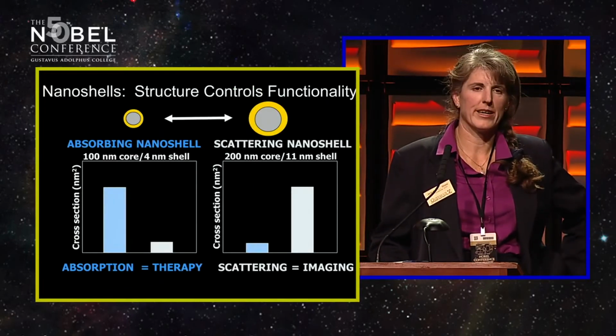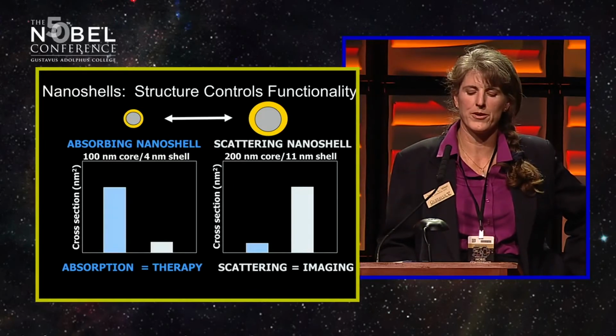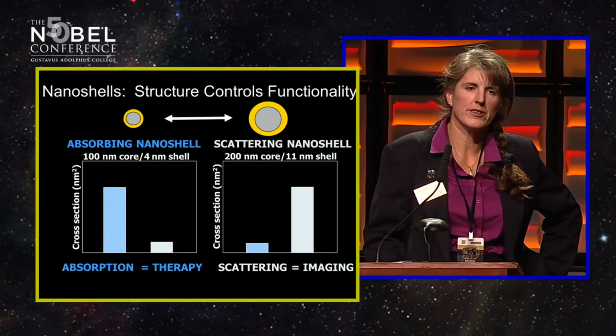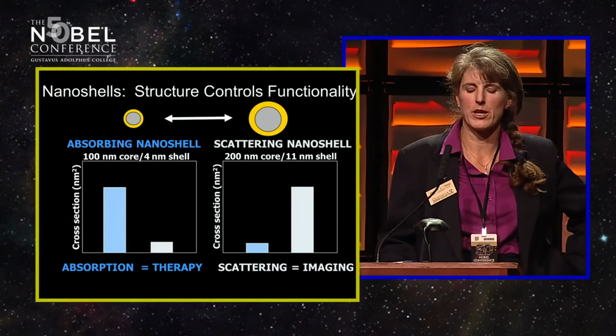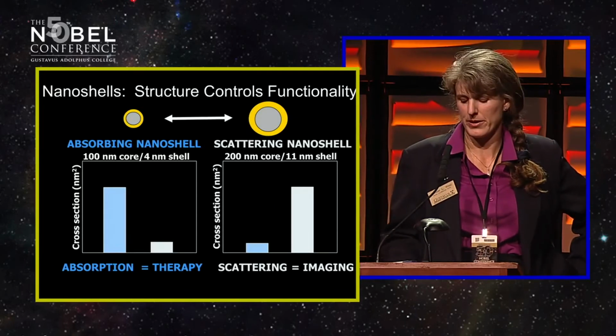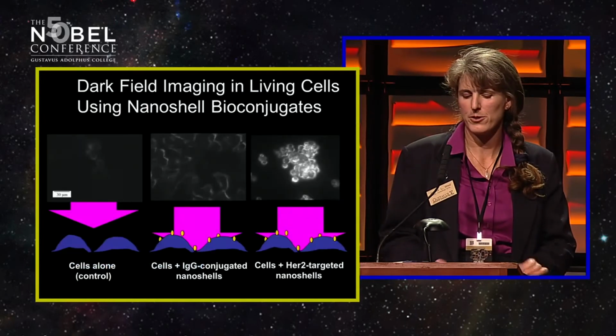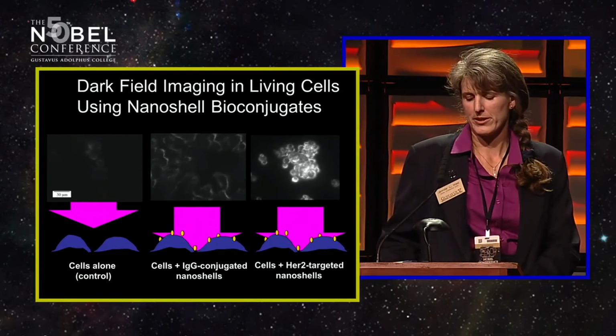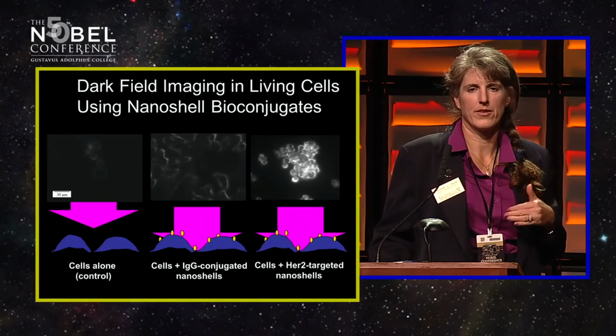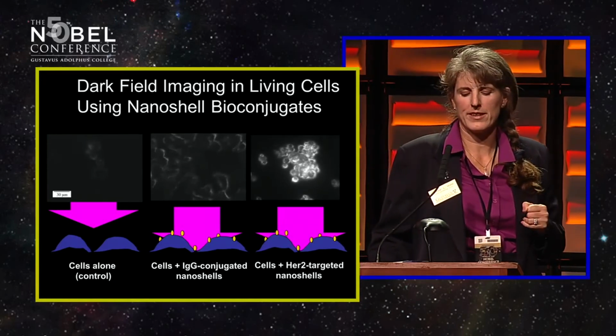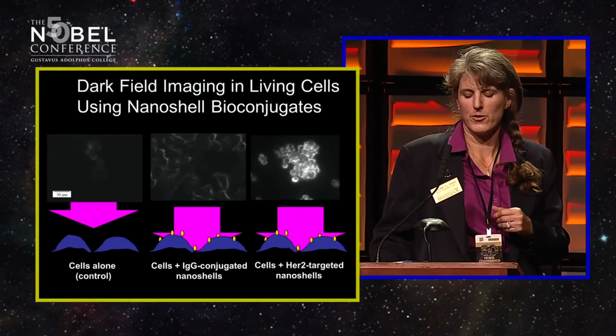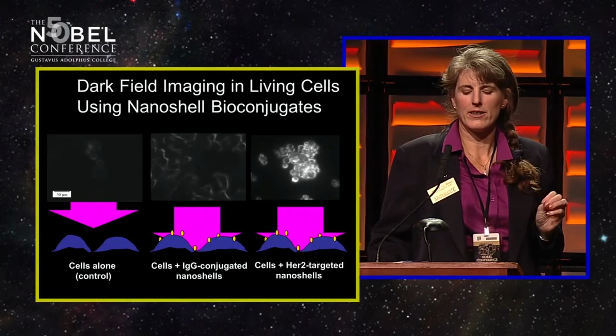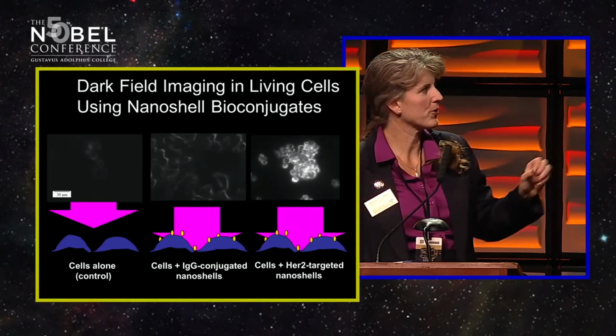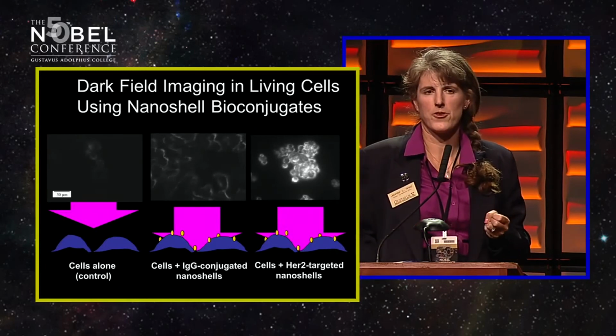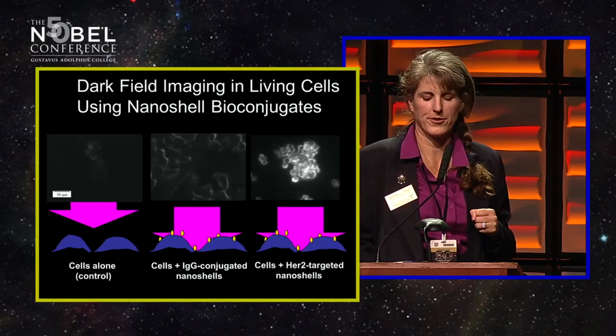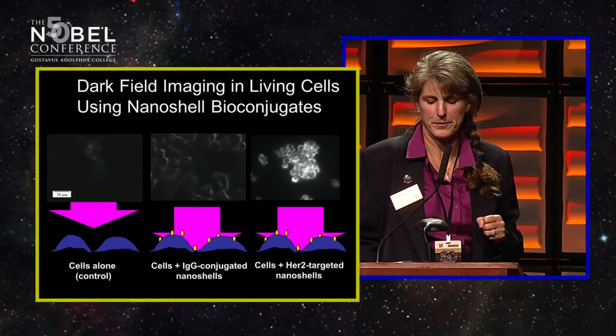So I've mentioned before, we can have our particles designed for absorption or for scattering for imaging. We've also looked at designing particles to be somewhere between these 2 extremes and to allow us to integrate imaging and therapy onto the same nanoparticle platform. So this is some work that was actually done by Rebecca Drezek's lab at Rice University, looking at the use of nanoshells for imaging. And so what you see is in the last condition here, which is the only one that's not a control, that you can see all of these tumor cells very nicely. We can see each individual tumor cell, they light up beautifully, and that's just due to the fact that the nanoparticles bound to their surface are scattering the infrared light very strongly.